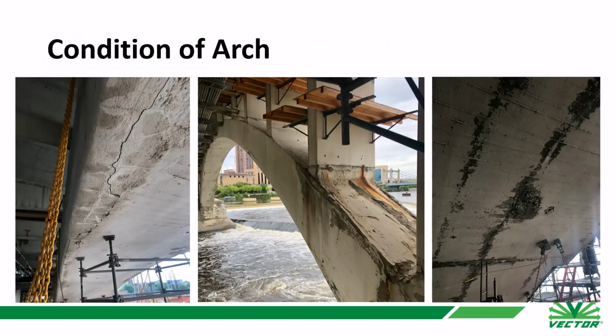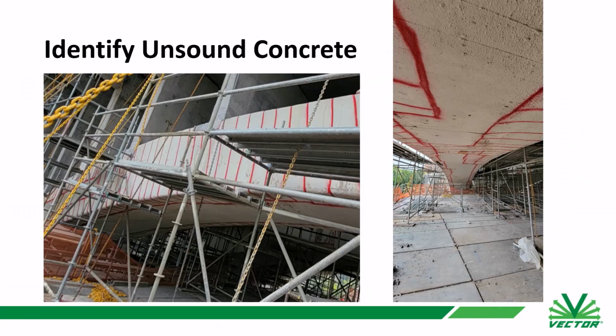And the problem that they have had over all these years is just leaking from the top down onto the substructure, and they really had severe corrosion of the corners, and particularly around these angles on the corners. And you see some of the cracking showing in areas of delamination, etc. And there was some isolated corrosion even on the metal pieces that were in the intermediate areas, not on the exterior.